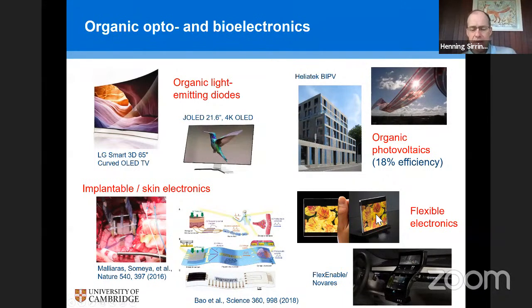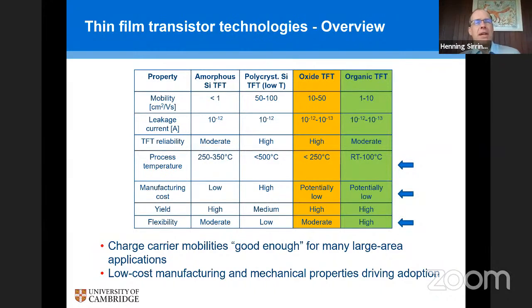So what you can see here are flexible liquid crystal displays, video displays that are not driven by amorphous silicon transistors, but by a backplane of organic transistors. And as I said before, this is not necessarily driven by organic semiconductors having completely outstanding transport properties. The field effect mobility of an organic transistor typically is between 1 and 10 centimeters squared per volt second, and that's lower than the best inorganic thin film electronics technologies. It's better than amorphous silicon, which is the material that's currently used, but some of the more advanced inorganic semiconductor technologies like polycrystalline silicon or oxide transistors have better mobilities.